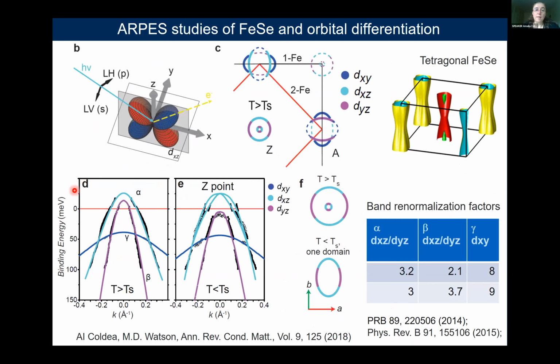And here is a summary of results in iron selenium and what we learned from it. So what we know in ARPES, it's quite a unique technique, because by using light polarization, we can probe different orbitals. So in a particular cut, we can be more sensitive to one type of orbital. This Fermi surface shows how the orbital configuration varies as we go around the Fermi surface. So you can have, this is in the tetragonal phase, a mixture of dxz and dyz orbitals.